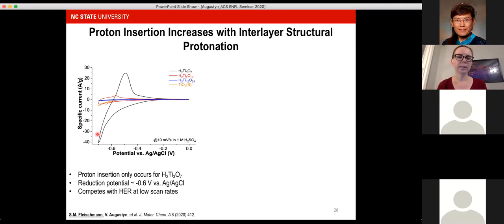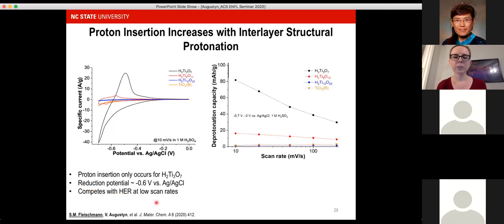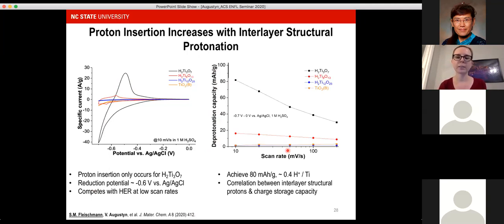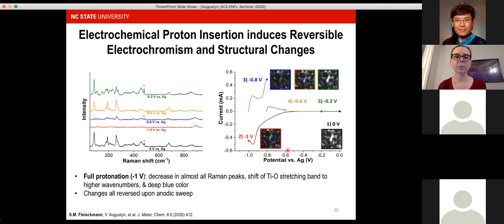This process, one of the downsides is that the reduction potential is pretty low. So we always had to go to very fast cyclic voltammetry scan rates to avoid the competition with the hydrogen evolution at low scan rates. This was the deprotonation capacity. So to avoid counting the HER current in our capacity, we only considered the deprotonation or the anodic capacity here as a function of scan rate. And we saw that we could obtain up to 80 milliamp hours per gram in these micron scale materials, which is about 0.4 hydrogens per titanium. And we saw this very strong correlation between the interlayer structure, the interlayer environment, and the charge storage capacity, with fairly good rate capability, I would say, even for these micron scale particles.